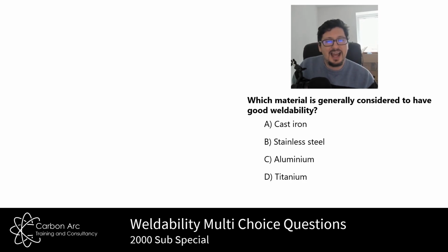Stainless steel and carbon steel, your standard carbon manganese steels, are really quite straightforward for a lot of the lower strength ones. So stainless steel, okay, you might need to back purge the back of root runs and things like that, but really we have quite a range of welding processes that can be used. We don't need to preheat because there's a very low carbon content. It's just generally quite an easy thing to weld without cracking. Okay, because that's weldability, remember: the ability to weld without it cracking.